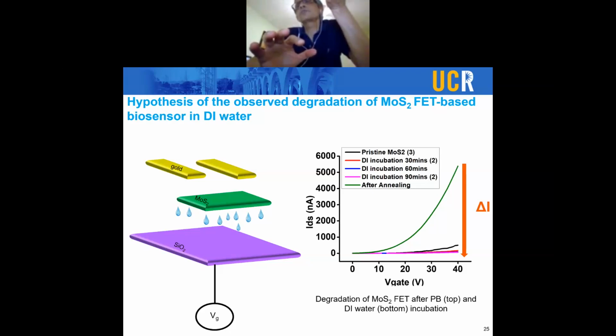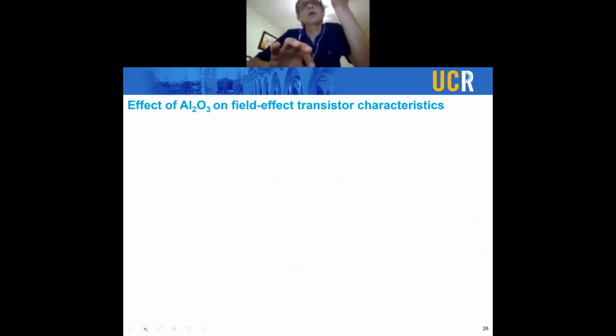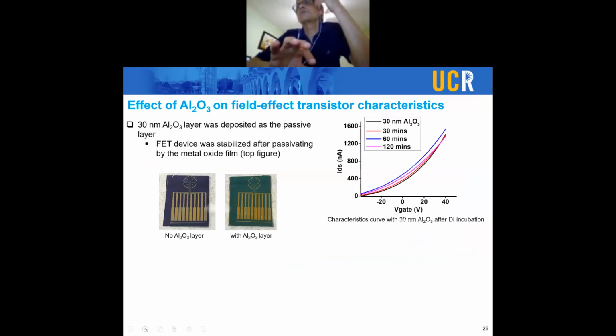So this is not due to sensing. What we concluded was that it was due to delamination of MoS2 from the surface of silicon oxide, because the water was seeping underneath the MoS2 layer and lifting it off. This is not what we wanted to do. So to eliminate this problem, we decided to create a layer of aluminum oxide on top of the MoS2 using atomic layer deposition. A very thin layer of aluminum oxide, 30 nanometers, was deposited.